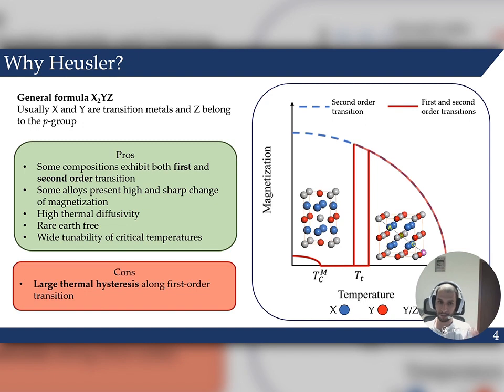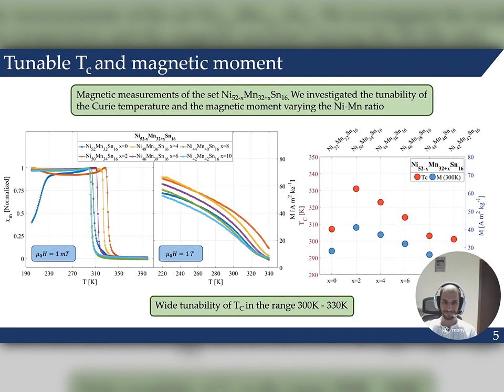But probably the property that makes the Heuslers very promising for this kind of application is the wide tunability of the critical temperatures of these alloys. In fact, it's possible to shift the magnetic transition temperature by slightly changing the composition of the compound. Unfortunately, many Heuslers exhibit a large thermal hysteresis across their first order transition, and this is the reason why the characterization and the test of thermomagnetic properties of our samples that we have conducted for the moment are only across the second order Curie transition.